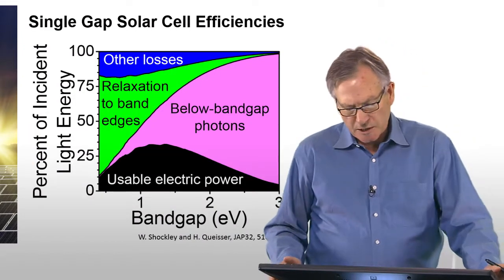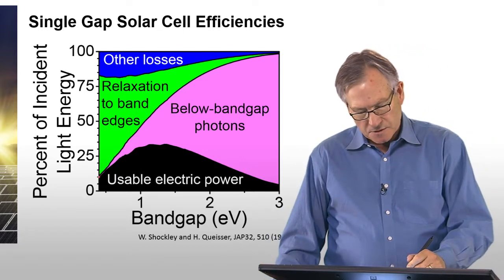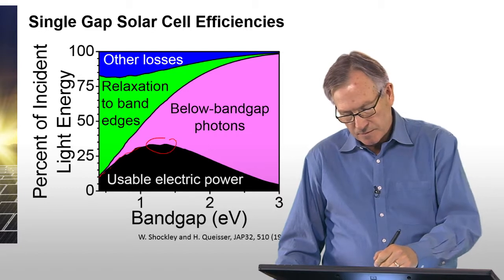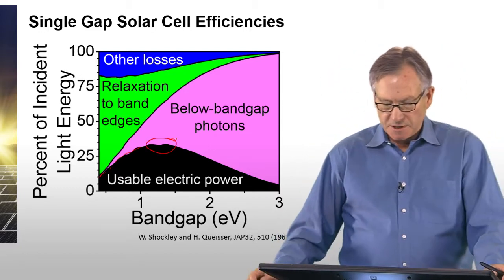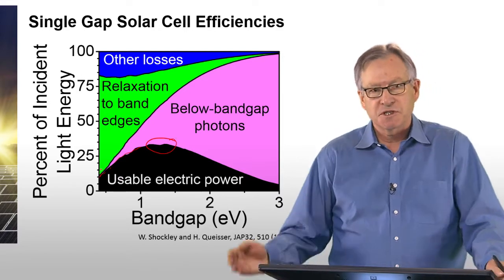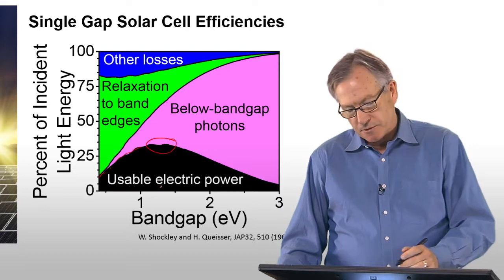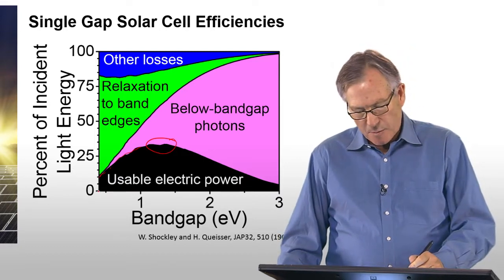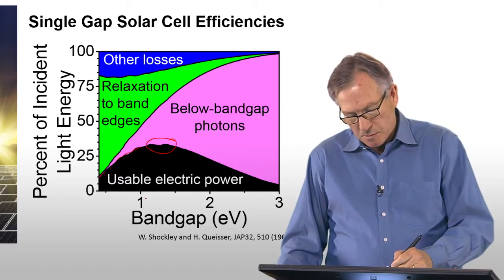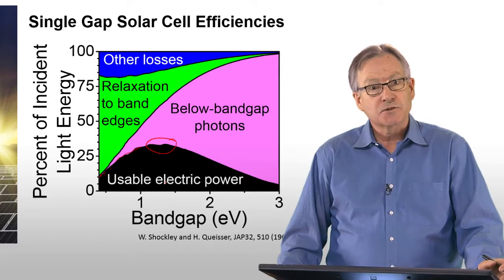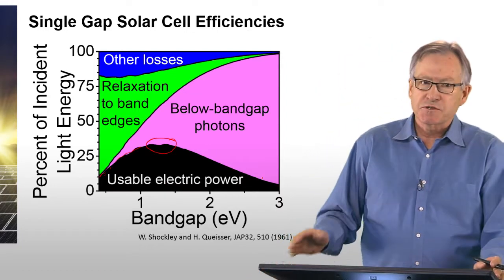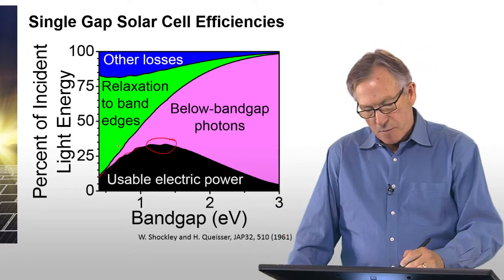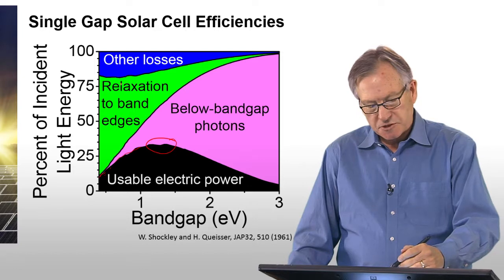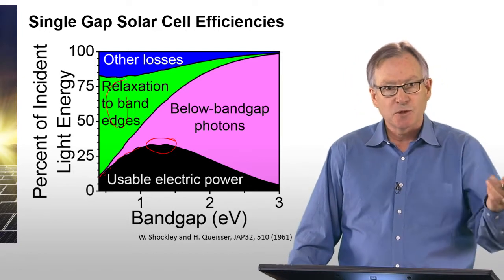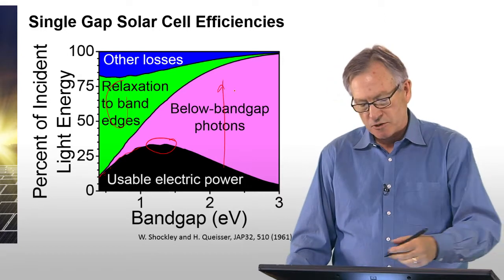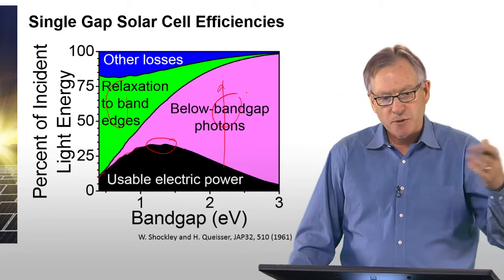This is another picture of the Shockley-Queisser analysis, and the Shockley-Queisser analysis is shown by this black curve down below. This shows the maximum conversion efficiency of sunlight to electricity as a function of the band gap of the material. As you can see, it starts off low at small band gaps, it increases and reaches a maximum between about 1.1 and 1.4 electron volts, and then it goes down again. And that's because of these two processes that I mentioned. For small band gaps, most of the photons are absorbed, but most of the energy is lost by this relaxation back to the band edges, thermal loss. For large band gap materials, most of the photons aren't absorbed, and so you lose the photons that are below the band gap.